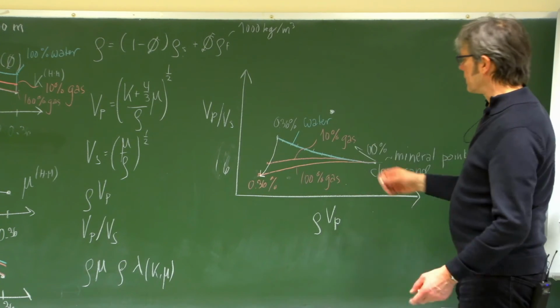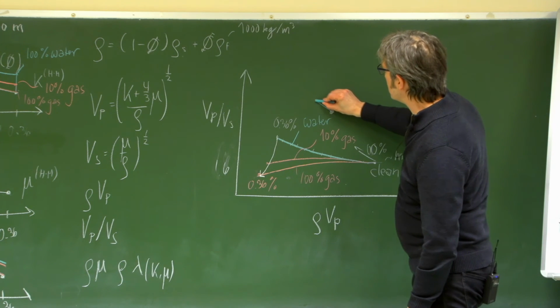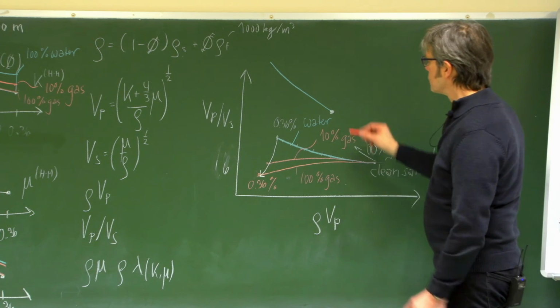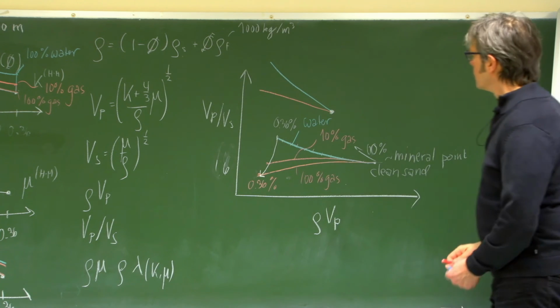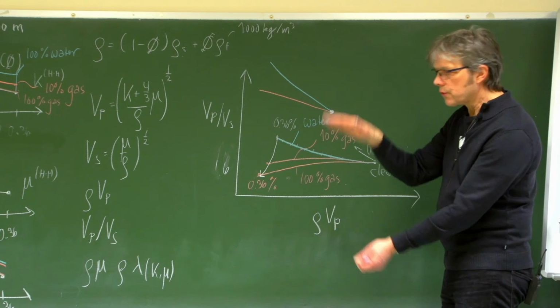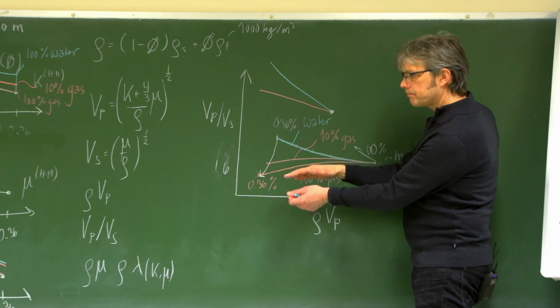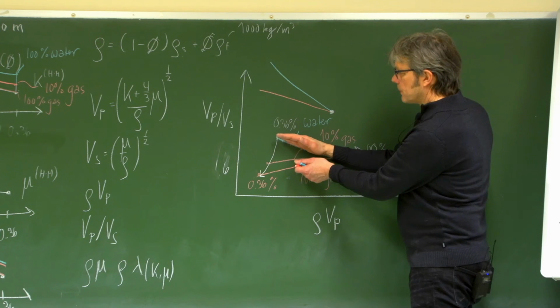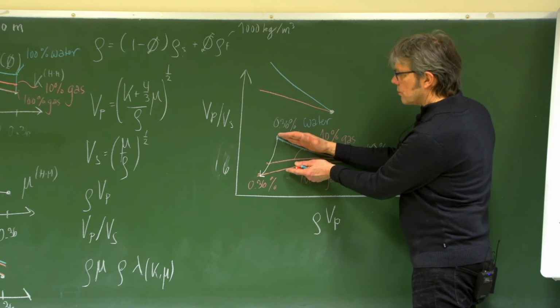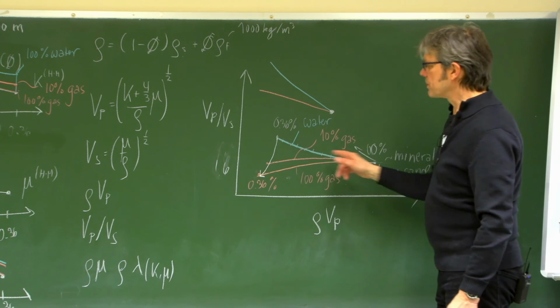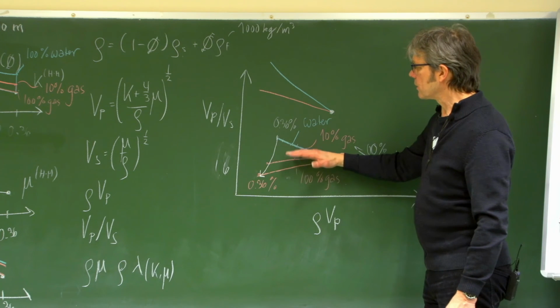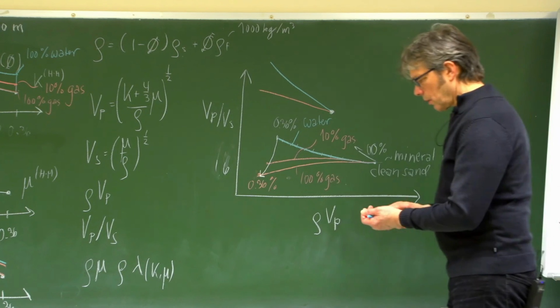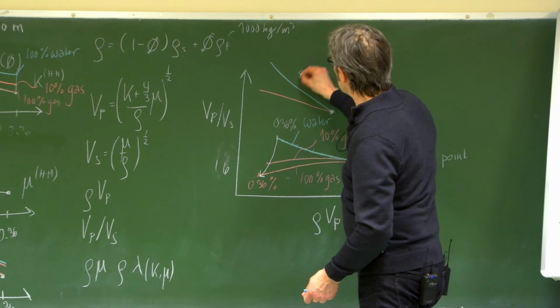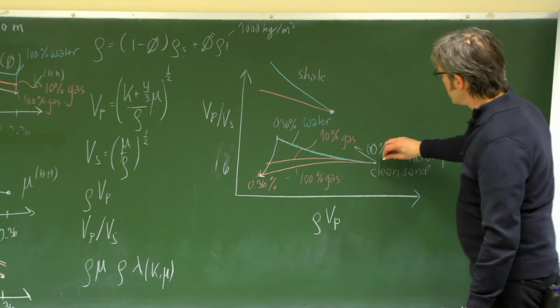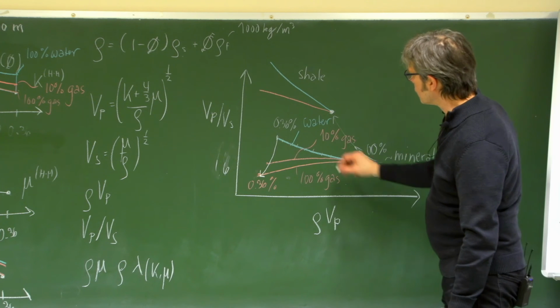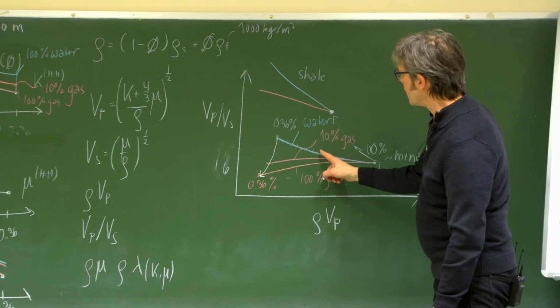And if I did the same again, I would see that my water-filled shale would move up like this. If I filled some gas into the shale, it would move something like that. So I used to call this the open mouth, where it's closing dependent on the type of fluid. So if you have water here, the gas here, and you get oil inside, it's closing a bit. So oil represents properties in between the gas and water, so we know that oil points would plot down here. But this is how a shale would move into this. So we see that the shaliness would move the points in that direction. So if I have pure sand and it becomes more shaly, I expect it to move in that direction.